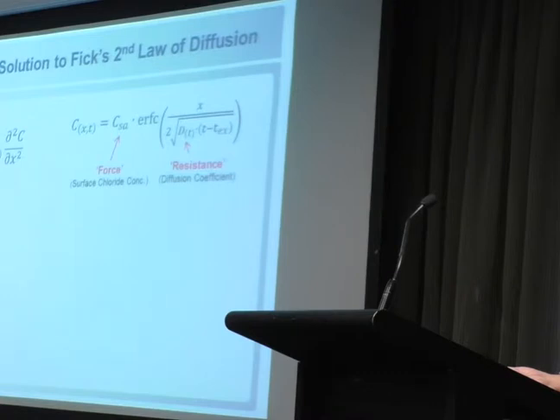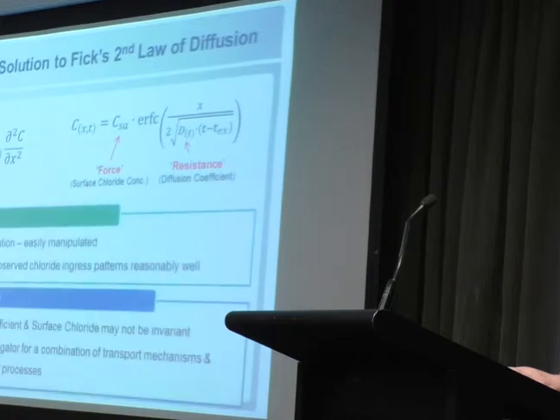And it's useful because it allows you to predict the chloride concentration at any depth in your concrete at any time, on the basis of two parameters that are very familiar to engineers, a force and a resistance: the surface chloride concentration that's accumulated on the face of your concrete, and the diffusion coefficient, which is a measure of its quality. And the advantage of that equation is it's simple, it's easily manipulated, you can do it with a spreadsheet, and as I think Jack said, you go out and look at chloride profiles in concrete structures, and that describes it reasonably well. Disadvantages are that the diffusion coefficient and the surface chloride may not be invariant. They may change with time.